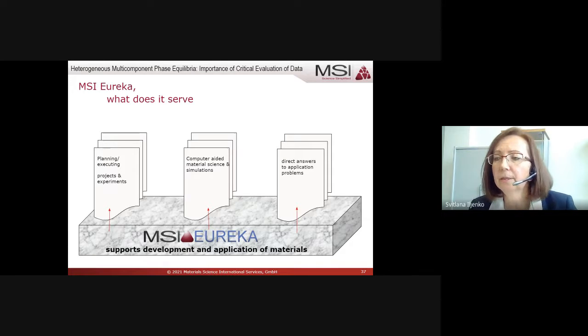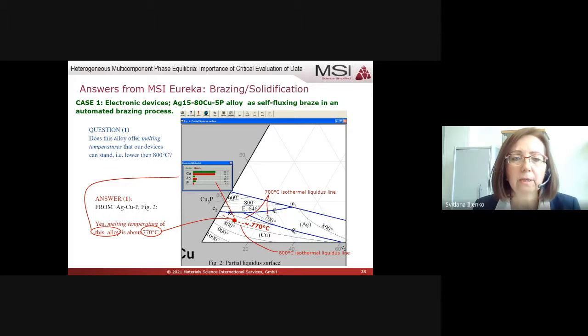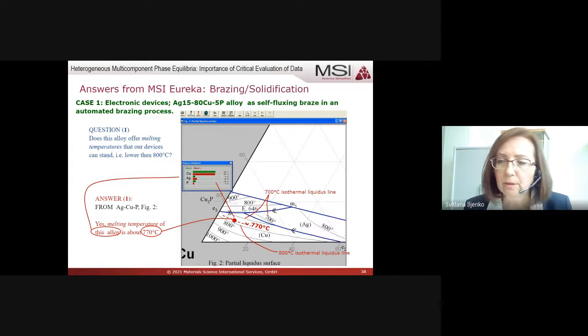A third area, just looking at a phase diagram, one can get direct answers in daily laboratory work. Let me show just some examples. In this case, for example, for the electronic devices with silver copper phosphorus alloy, does this alloy offer melting temperatures that our devices can stand, means lower than 800 degrees? The answer is coming from the liquidus surface of this ternary system. One looks at the composition of this alloy, it is here. It is located between two isothermal lines on the liquidus surface, 800 and 700. So one can estimate it as 770. That means that this alloy, which somebody would like to use, is possible to use in this device.